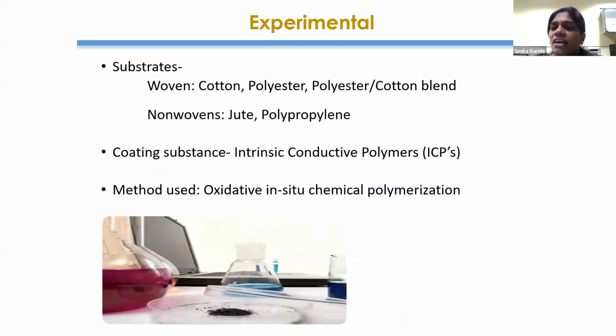Now, in BTRA, we have applied polypyrrole and polyaniline over various types of materials, on woven samples and also on non-woven samples. We have applied these polymers over cotton, polyester, cotton blend, and nylon fabric, and for non-woven, we have applied them on jute and polypropylene. The method which we have adopted here is oxidative in situ chemical polymerization.